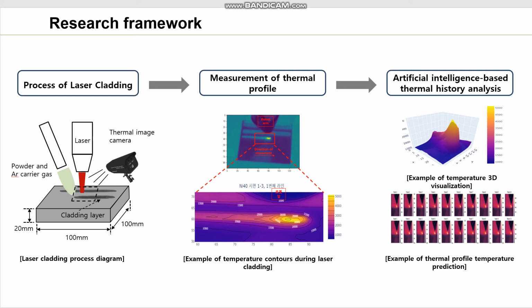In the case of laser cladding, as the process progresses, overheating causes thermal distortion, cracking, and excessive dilution in the heat effective zone. In order to prevent these quality problems, it is important to be able to control the thermal profile in the heat effective zone. In other words, quantitative analysis of the heat effective zone is necessary for quality control during laser cladding.